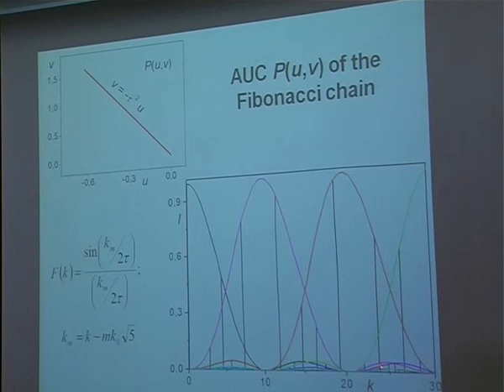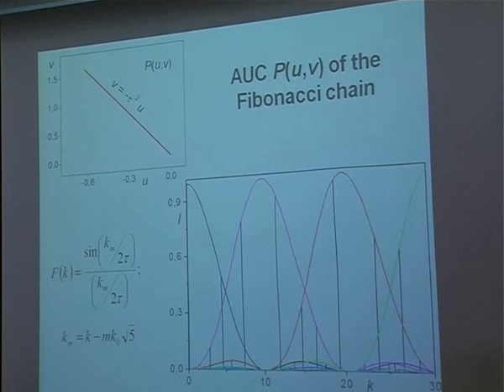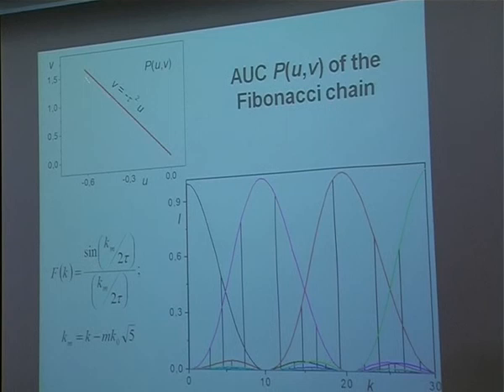The diffraction pattern consists of periodic series of diffraction peaks and satellites. Unfortunately, the satellites are incommensurate compared to the main diffraction peaks. So the diffraction pattern looks very complicated, but it is simply the Fourier transform of this rectangular distribution.